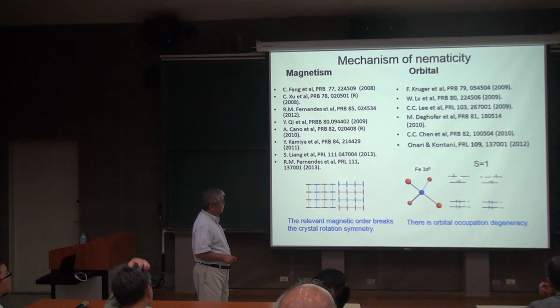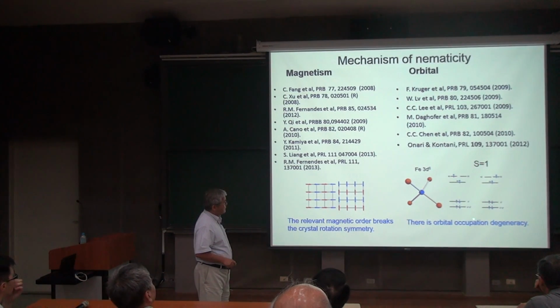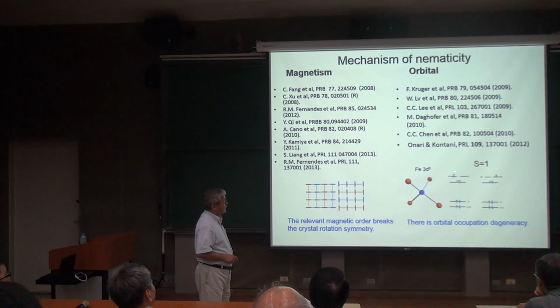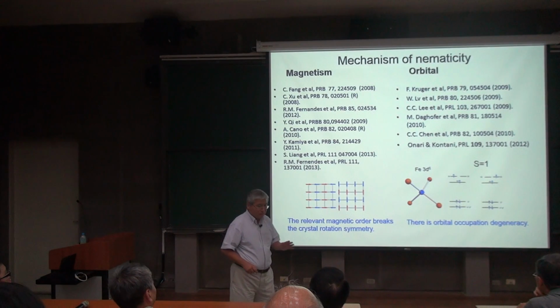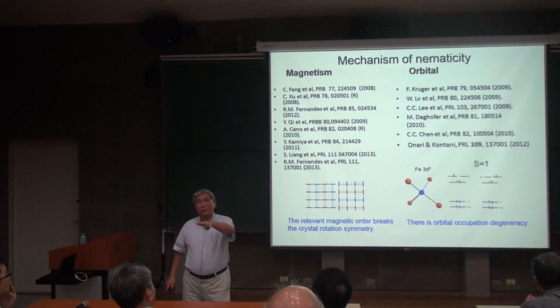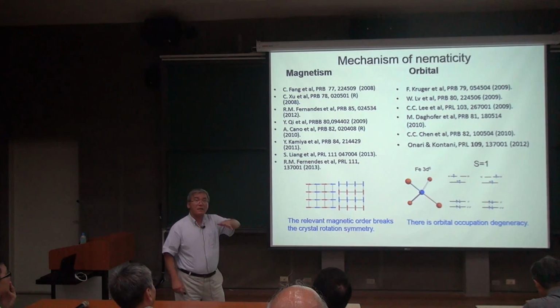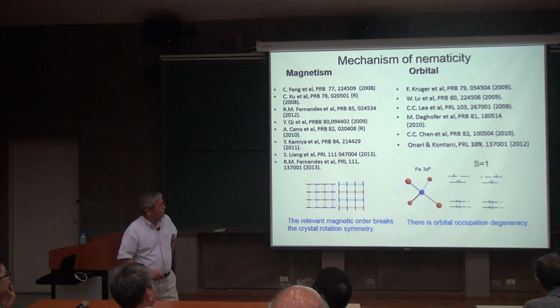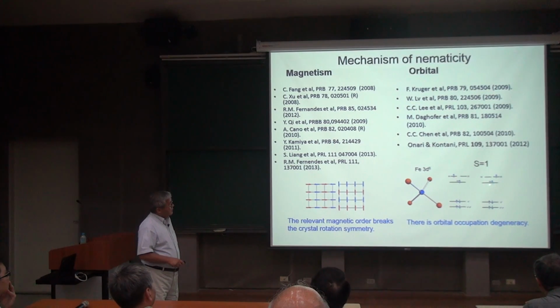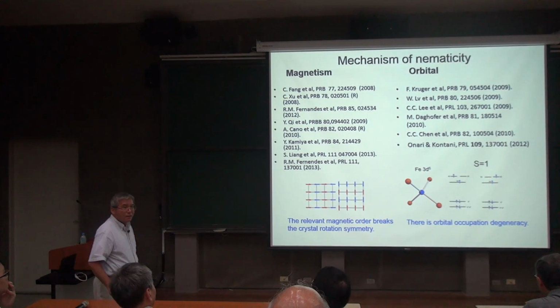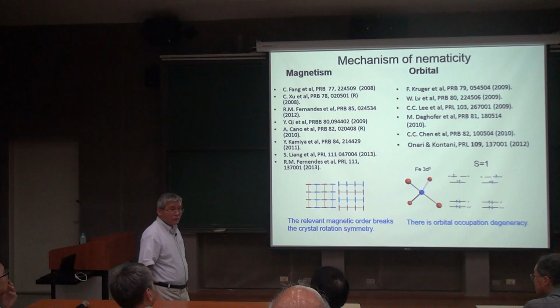But in this case, there are 2 possible occupation patterns, and these 2 occupation patterns differ from each other. Which one of the topmost 2 levels do I occupy? You probably cannot read it, but this is the dxz orbital, and this is the dyz orbital. So if I choose to occupy this pattern, then xz and yz symmetry is spontaneously broken. That means a 90-degree rotation, because if I rotate xz by 90 degrees, it becomes yz. So 90-degree rotation in this scenario is caused by such a breaking of the occupation degeneracy, and that's called the orbital mechanism. Those states are indeed degenerate.